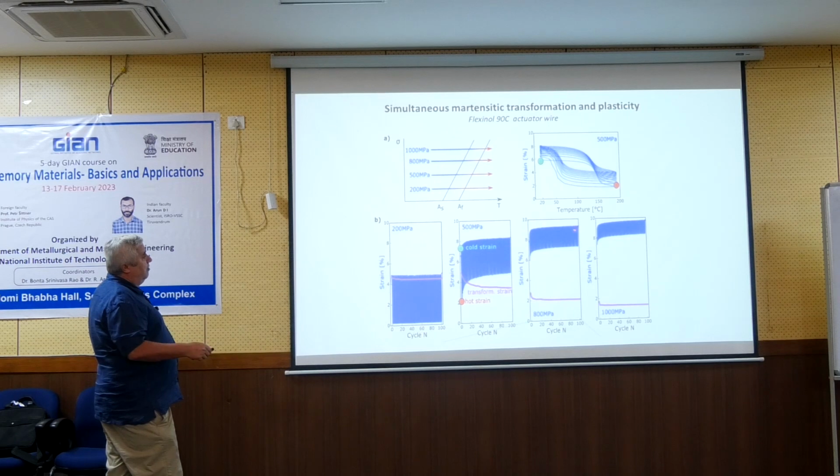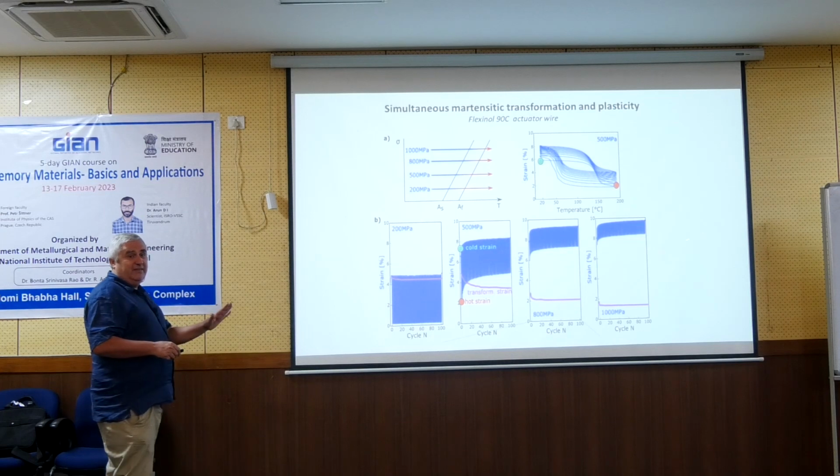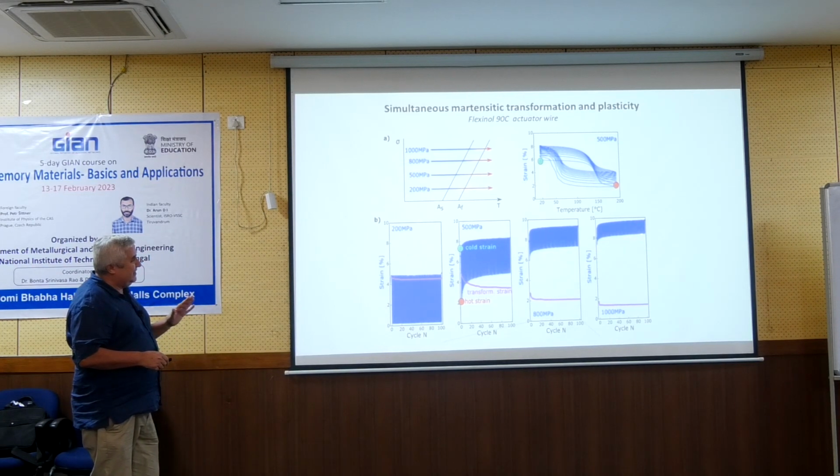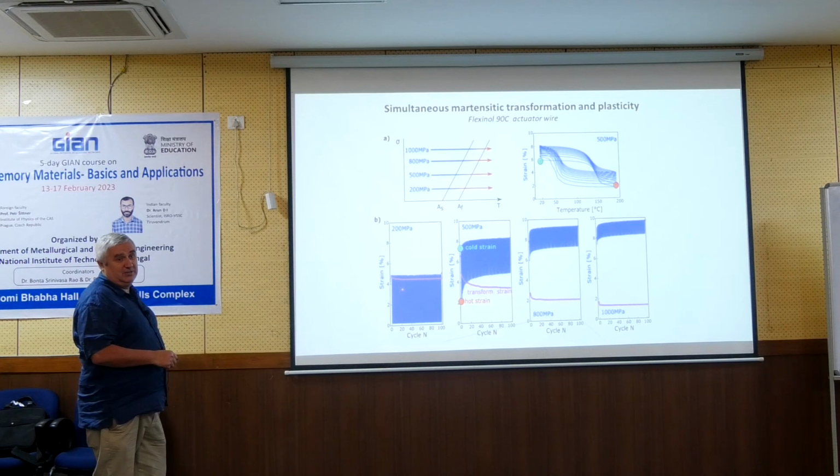And if you go more, even the amplitude of your oscillation will go down to 2% only, and it will be shifted 8%. But still it works. So somehow you don't have to be frightened. Because even this material, you can cycle it for thousands of cycles, but it will break. This you can cycle for millions of cycles.